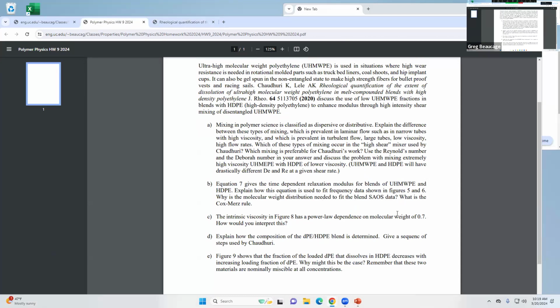So you can say, well, this solvent isn't exactly good, but you can also say if it's a branched chain, the dimension in the good solvent probably goes to a little bit larger dimension. That would make this Mark-Houwink coefficient go from 0.8 to something smaller than 0.8, like 0.7. That probably indicates they are branched chains and it's in a good solvent.